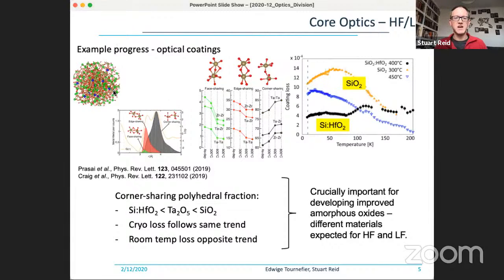This work by Kiran Prasai in Stanford was looking at atomic simulations. Here are some grazing incidence pair distribution function studies where the atomic structure was analyzed. There were some particular features within the tantala coatings that they were looking at in relation to face shearing atomic structure, edge shearing, and corner shearing. When we looked at how these atomic structures varied with annealing, now typically when we increase the annealing temperature, we decrease the mechanical loss, and we saw that face shearing structures decreased, as did edge shearing, but corner shearing increased. And so there was an implication here that, in fact, for room temperature coatings, if we're using oxides, we want atomic structures which are preferring this corner shearing atomic network.